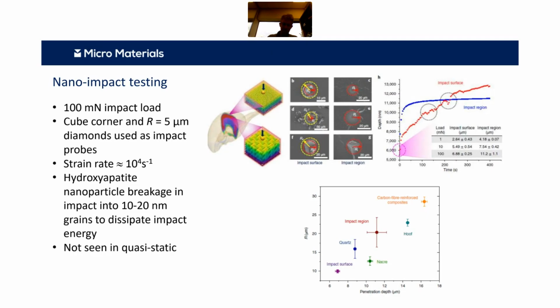They generate these high strain rates for the test, so these are much higher than you can achieve in normal nanoindentation, where you're maybe limited to 10 to the -1 per second, and typically you're working at much lower strain rates to get that quasi-static contact. So you can see, if you look on the right, the example there of a multiple impact test, and there you can see that different parts of that structure will have completely different impact behavior. So the initial damage is rather similar, but then with multiple impacts, you can see there are very clear differences in terms of how these structures behave. And there are different deformation mechanisms that you see in impact that you don't see in quasi-static testing.